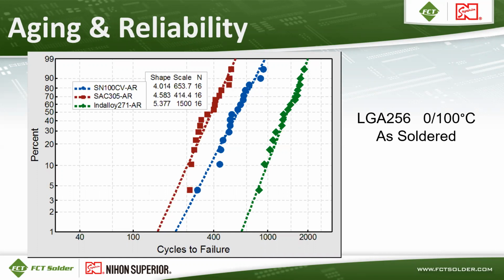Here's data for the LGA 256 with a different temperature range from 0 to 100 C. So this is data as soldered. And what you've got in the red squares are SAC 305, the blue circles are SN100CV, and the green diamonds are Indalloy 271, which had the longest life. SAC 305 had the shortest life as soldered.